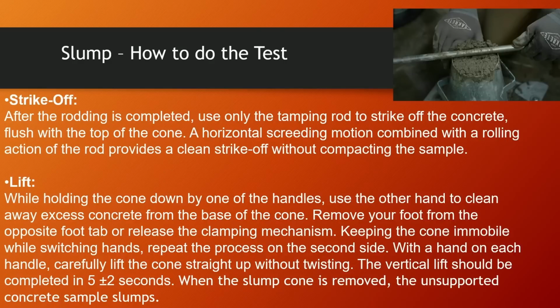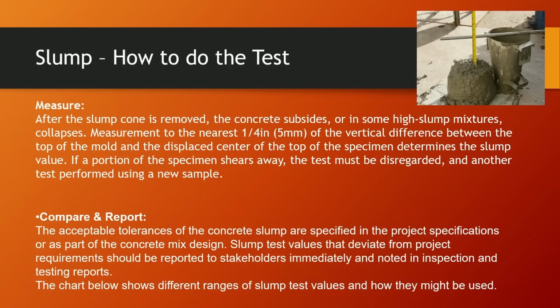Don't twist. Vertical lift should be completed in 5 plus or minus 2 seconds. They actually count when you take the test. It really does matter per ACI. This is how you have to do it. When the slump cone is removed, the unsupported concrete sample slumps. And that's what you're going to measure.